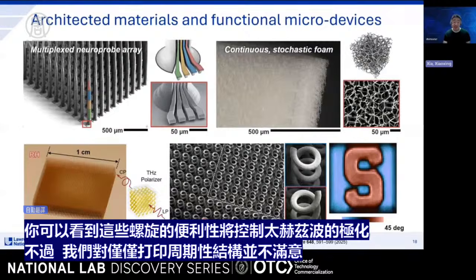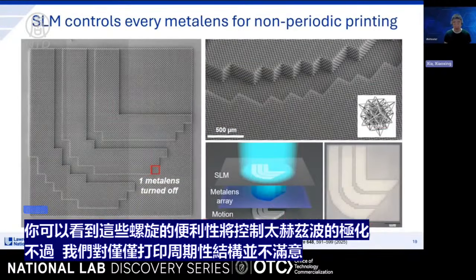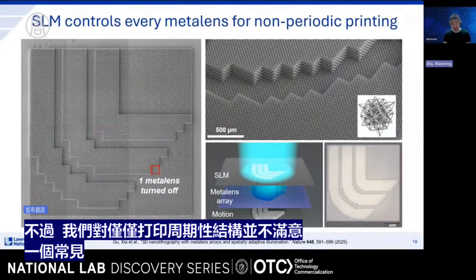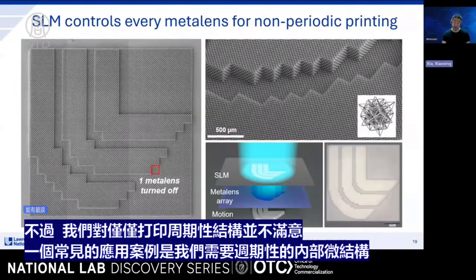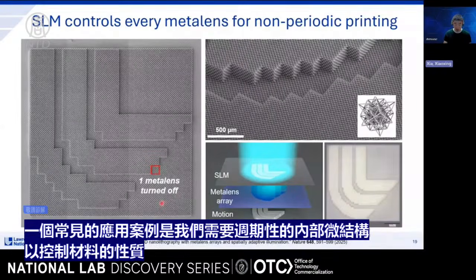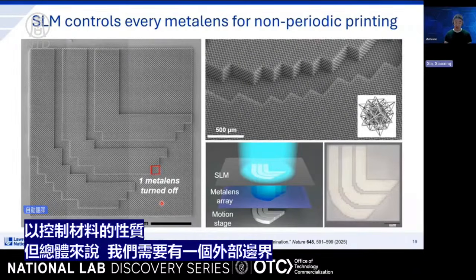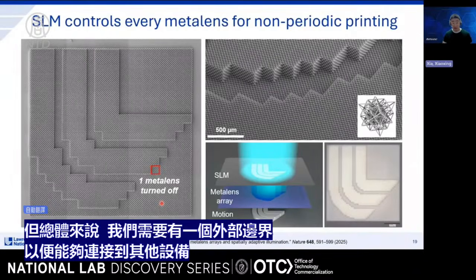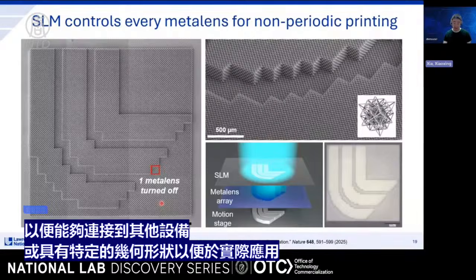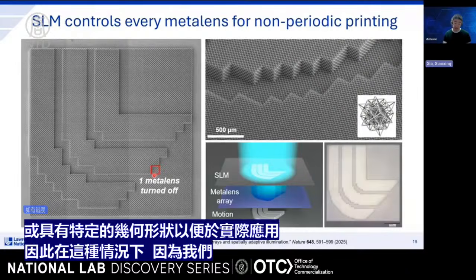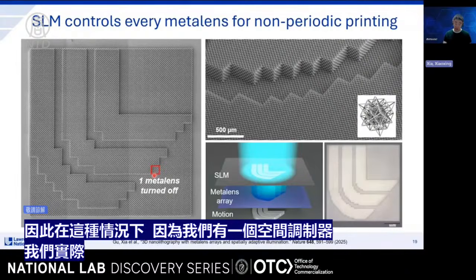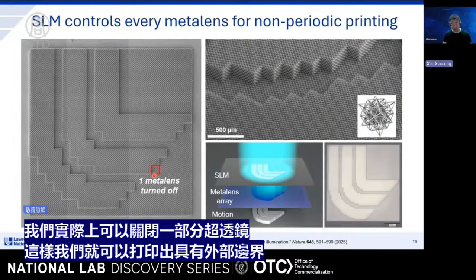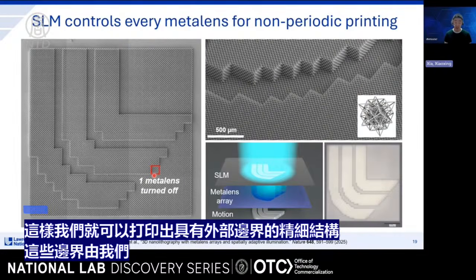But we're not satisfied with printing only periodic structures. One common use case is that we need a periodic inner microstructure that can control the material property, but overall we need to have an exterior boundary that can connect to other devices, or have specific geometry for actual practical deployment. So in this case, because we have a spatial light modulator, we can actually turn off a subset of metalenses so that we can print very intricate structures with an exterior boundary that is controlled by our spatial light modulator mask.